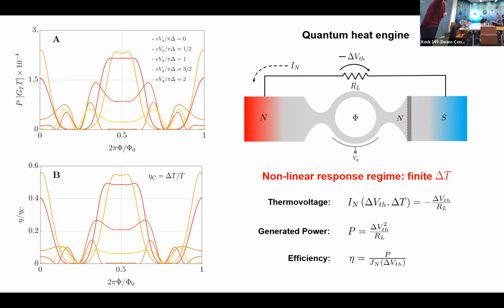You see, for example, for high Vg, you have the best efficiency. Otherwise, if you change it, the efficiency goes completely down. But then it really depends on the phase, because if you swap the phase again, you get better results. And Vg is just the gate voltage. Indeed, it's just an extra dynamical phase that the electrons acquire. Basically, Vg times the length of the lower arm is the extra phase that you take only if you go through the lower arm.